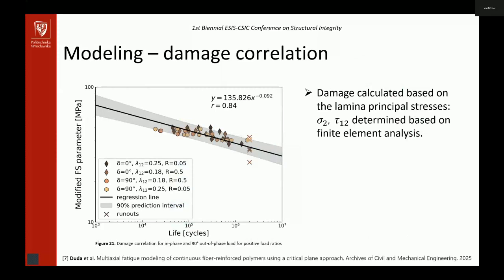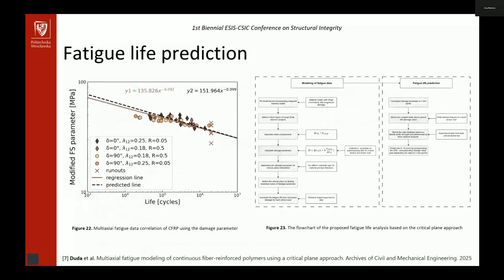So, the damage correlation. The results which are connected with the damage parameter have been shown here. We see the R squared is equal to 0.84, with 90% prediction intervals. Based on this, the damage here was not calculated based on the stresses that were plotted on the S-N curves, the geometrical ones. They were calculated based on the finite element model for the mesoscale stresses, sigma 2 and tau 1,2.